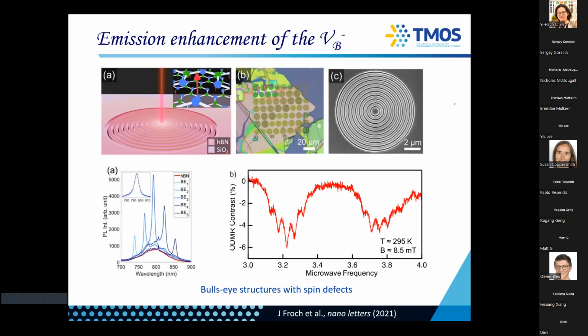So what do we do? We make bullseyes, and we know how to work with hBN. So we pattern these lenses. It's called a bullseye cavity, but officially it's just an antenna. It has almost no Purcell enhancement. It just collects more light. And you can see that you can collect much more light at around 800 nanometers.